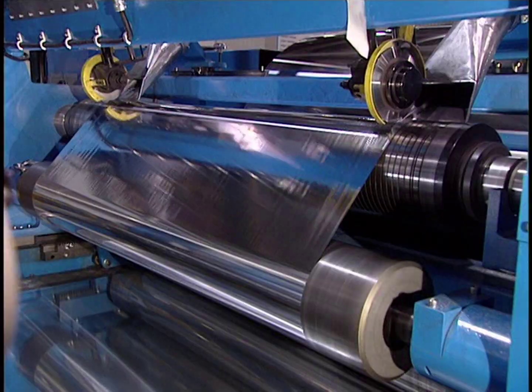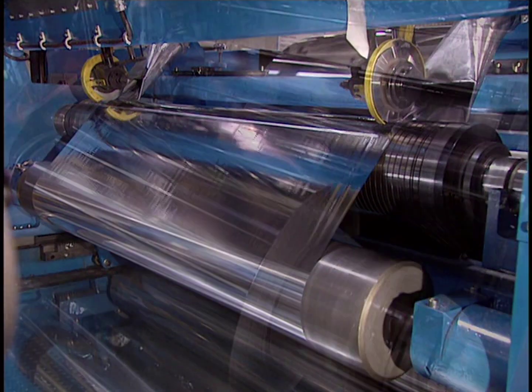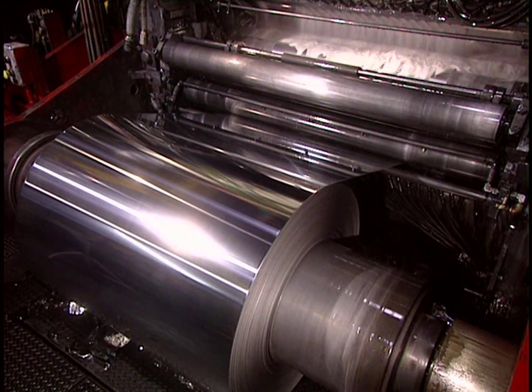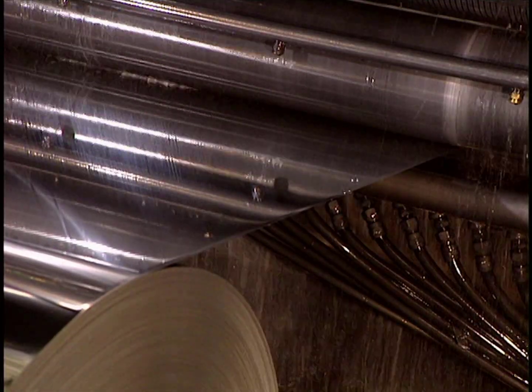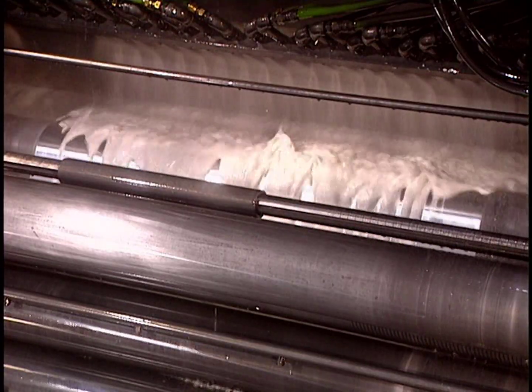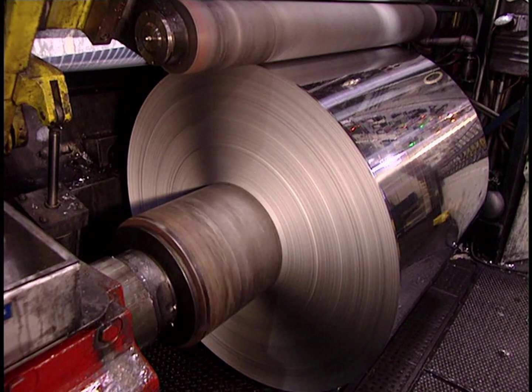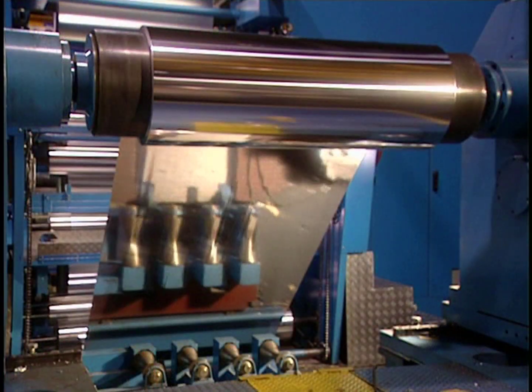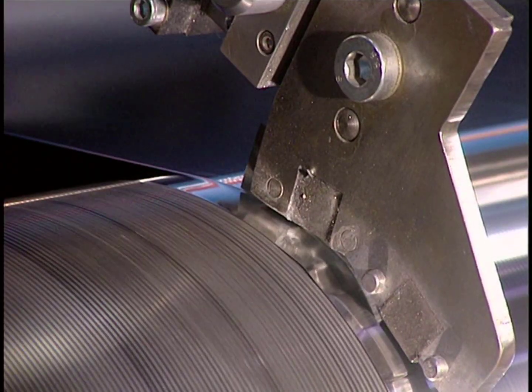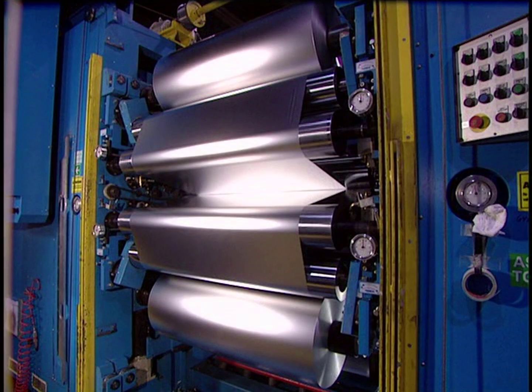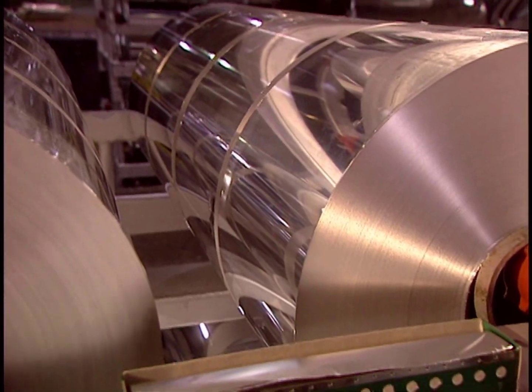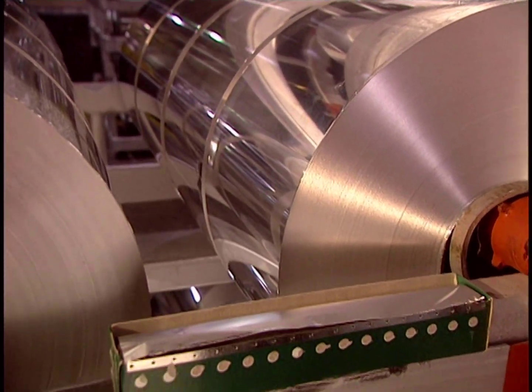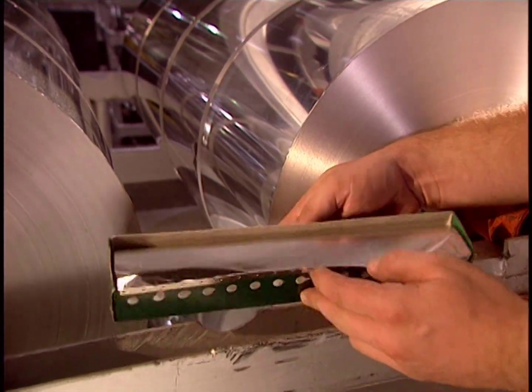One final reduction in the mill, and the sheet will have the thickness required by the customer. A liquid coolant is used to prevent the foil from sticking to the rollers. Since the edges of the foil sheet are lightly damaged and crinkled, a knife removes a strip 4/10 of an inch wide. Finally, the roll is cut to the desired width, and one huge ingot has produced nearly 8 miles of foil.